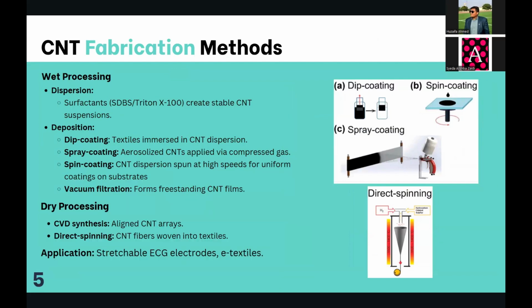Then let's move on to CNT. CNTs are fabricated in two ways, wet and dry processing. For wet processing, first surfactants like SDBS, which is sodium dodecyl benzene sulfonate, or Triton X100, break apart CNT bundles into stable suspensions. Then we deposit them using one of the four techniques.